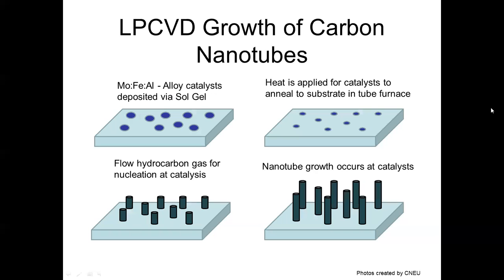So this shows us a schematic of the growth of carbon nanotubes with the catalyst. And again, what we're doing here is we're preferentially depositing a catalyst over a local substrate. What the substrate is going to do is provide a template to grow the chirality on the tube itself. And so what will happen is when the hydrocarbon gas is flown across the surface at a high temperature, what it will locally do is go into the catalyst area, supersaturate the catalyst. Once the catalyst is supersaturated, it has no choice but to try to minimize its energy. How it's going to do this is it's going to nucleate that particular gas alloy on the surface, such as the carbon. So the carbon will form bonds to the surface, allowing this system to minimize its energy. After it does that, of course, it's going to supersaturate again from the inflowing carbon gas to further make a nanowire.